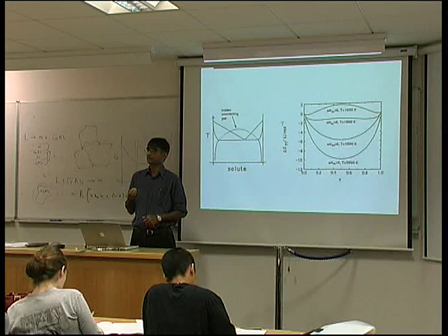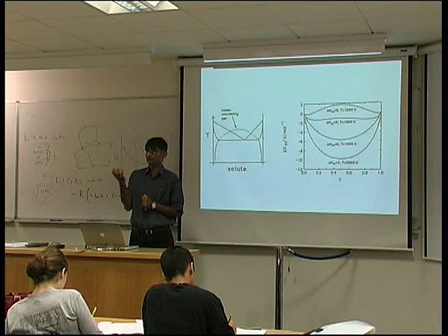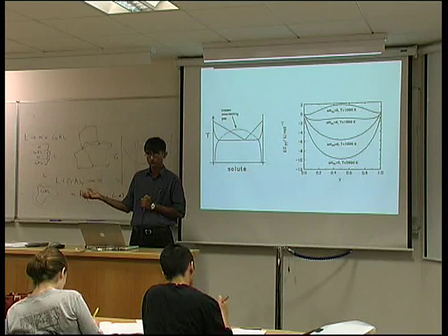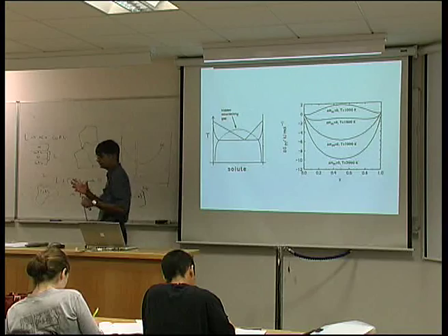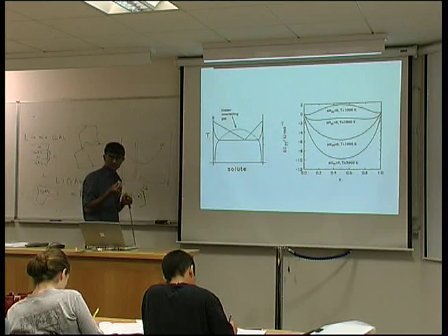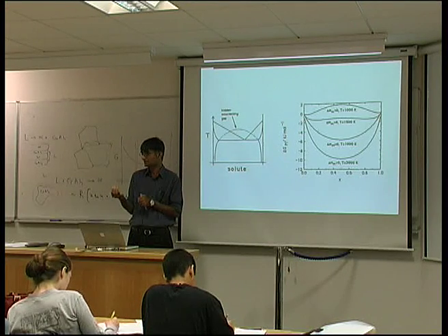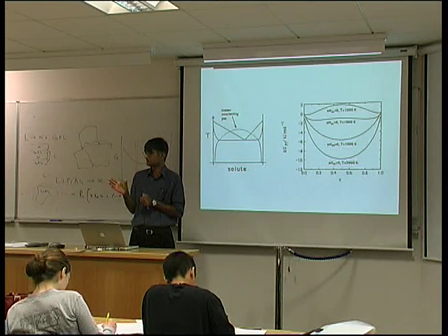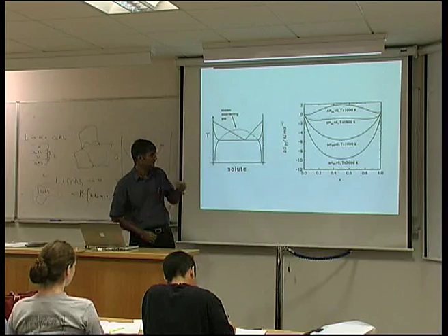Now, supposing that there is a change in binding energy when I break an AA bond and a BB bond to form two AB bonds, then that change can be of two kinds. One is that there is a reduction in bond energy. In other words, A atoms prefer to be next to B atoms. So that would be a system where you get a minimum in free energy when you have equal numbers of A and B atoms.